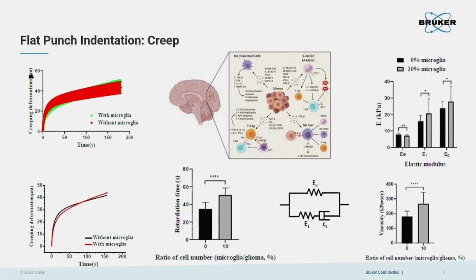After that, we use this model to characterize this creep behavior. So we have totally three components in the viewpoints of mechanical properties. One is the elastic modulus. The other one is a Kelvin series, including a stiffness together with a damping coefficient. So the stiffness means another modulus, and the damping coefficient means the viscosity. So it is an idea of viscoelasticity understanding.